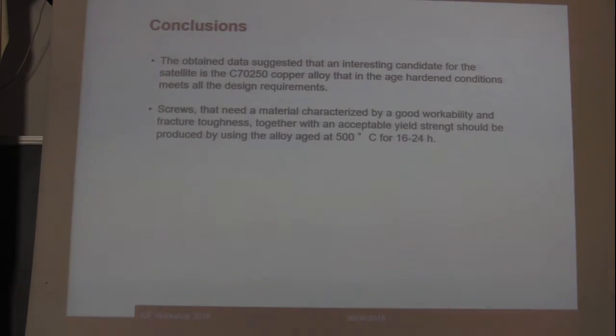As a conclusion, the data obtained with this study suggested that the most interesting candidate for the satellite is the C70-250 copper alloy in the age-hardened condition, because it meets all the design requirements. Screws that need to be characterized by higher toughness and workability could be produced by using the alloy aged at 500 degrees centigrade for 16 to 24 hours.